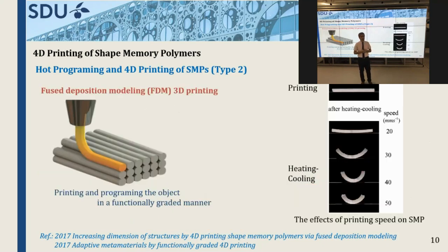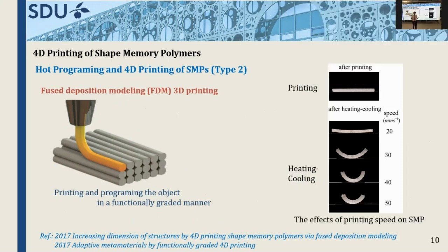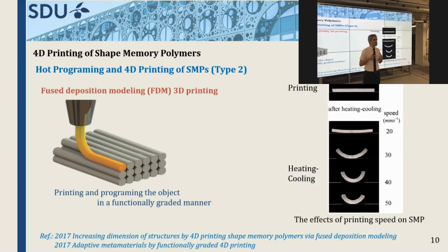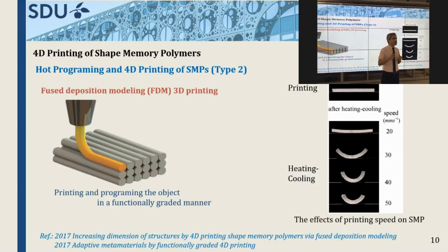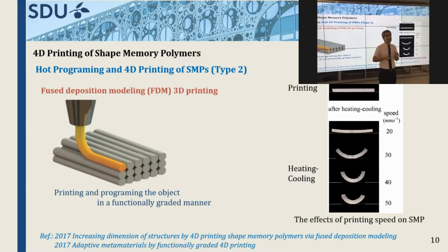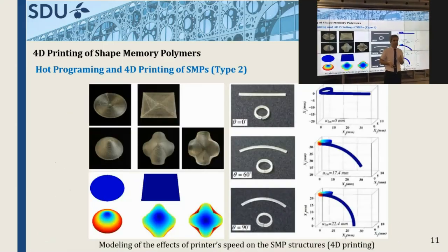The key point of this phenomenon is that every structure made by FDM process or other additive manufacturing technology is made by a sequence of layers. Based on the moving speed and also the temperature gradient inside of the material, some strain is induced inside of the structure. This strain can be recovered by heating and cooling. Here, in the right-hand side picture, we have a ribbon made by shape memory polymer. After printing, this material is subjected to heating and cooling process. Depending on the printing velocity, as you can see, we have different curvature after heating and cooling.